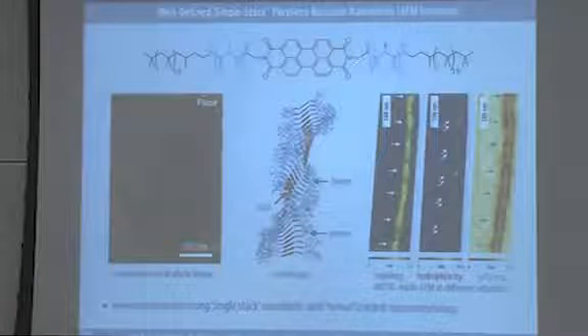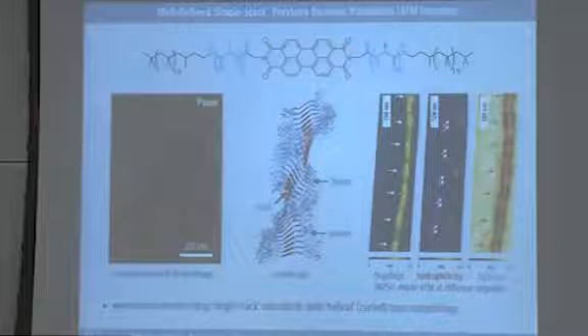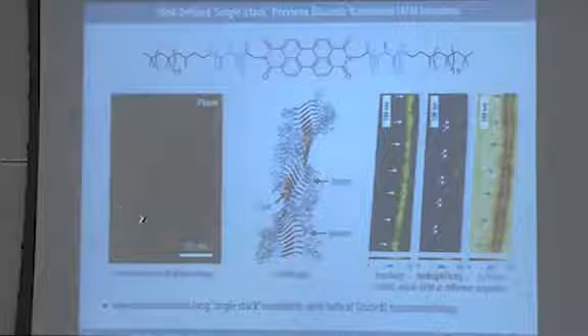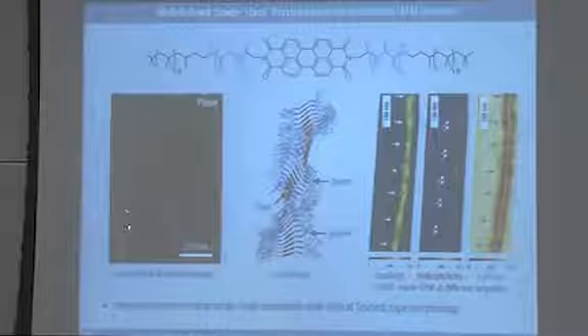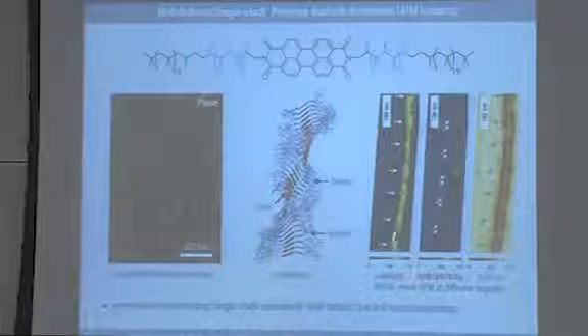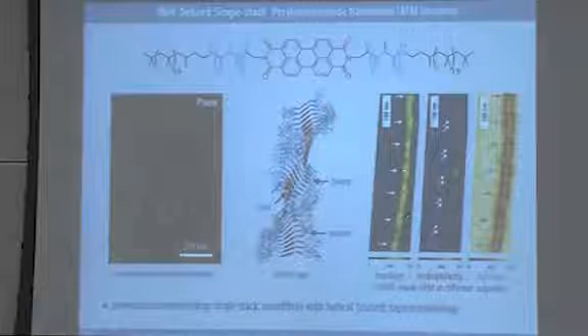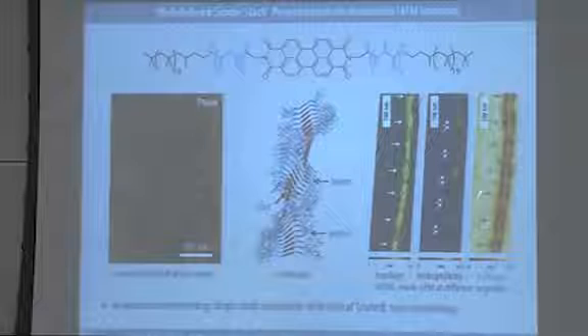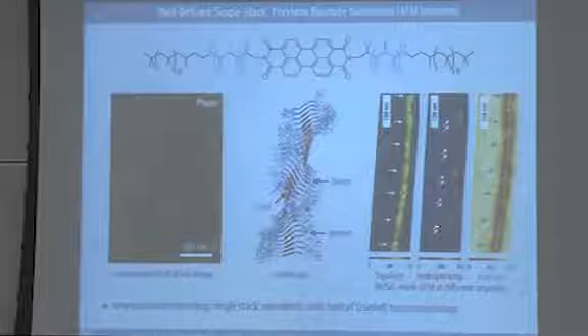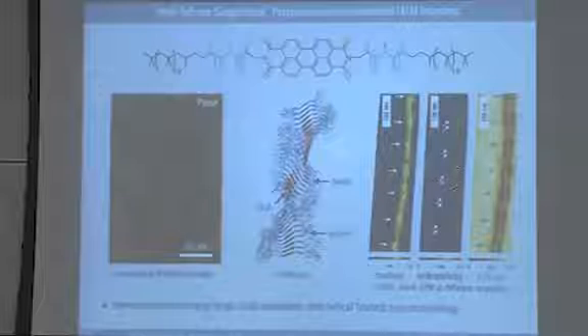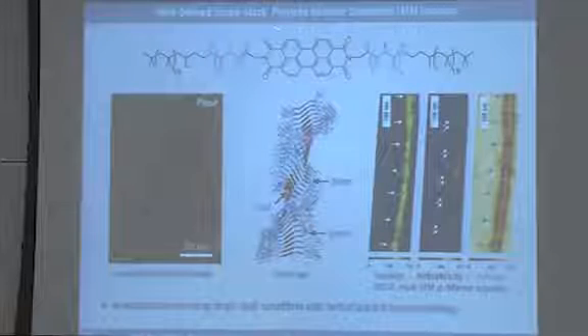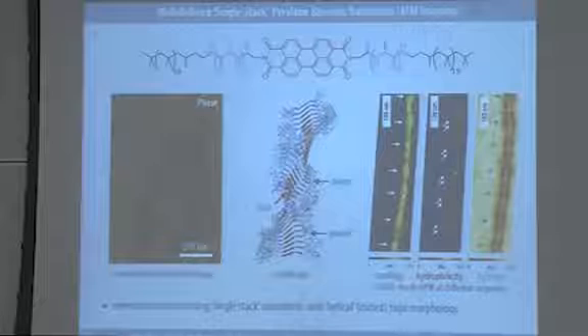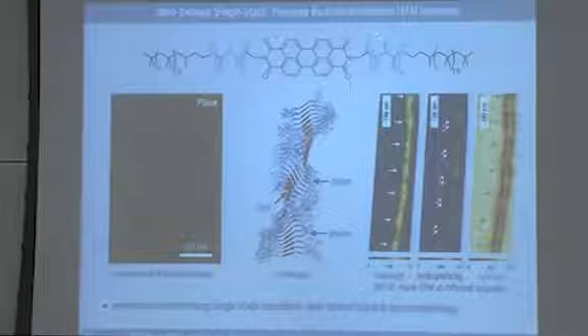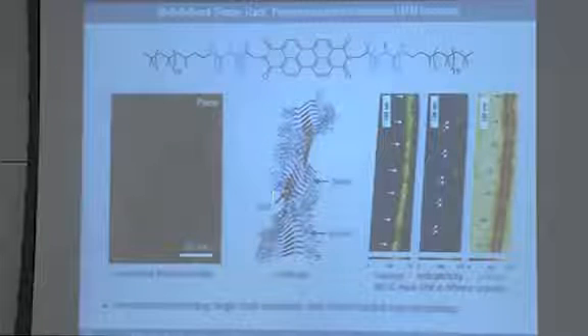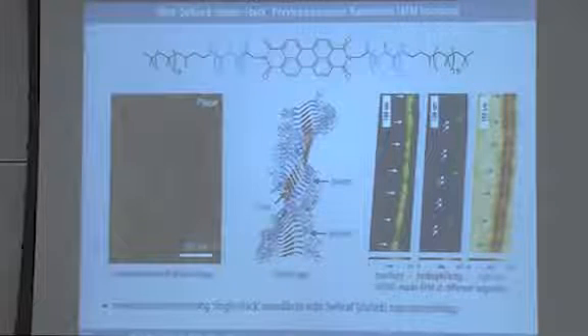And we can finally even exchange the core from a donor type molecule to an acceptor type molecule. And again, conventional AFM images show nicely defined fibrils, again with a helical morphology. And the MUSIC mode images in this case again show height corrugations. And in this case, the hydrophilic-hydrophobic image shows two lines running diagonal where the bumps are. And so one can tentatively attribute this to the hydrophilic contrast from the oligopeptide perylene bisimide oligopeptide segment, schematically shown here, so that you obtain these diagonal stripes.